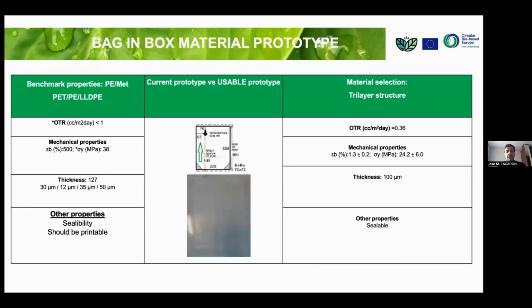Then there was this bag-in-box application, which was extremely challenging because it required an oxygen transmission rate which today is obtained by combining different materials, metallized PET or EVOH, high barrier polymers in general, and low-density polyethylene, etc. So the critical parameter was to obtain an oxygen transmission rate better than 1 cc per square meter per day, and we were successful on that while maintaining relatively the same thickness. It would have to be, of course, sealable, and this was all achieved, and our OTR was in the range of 0.36. So that was very good.